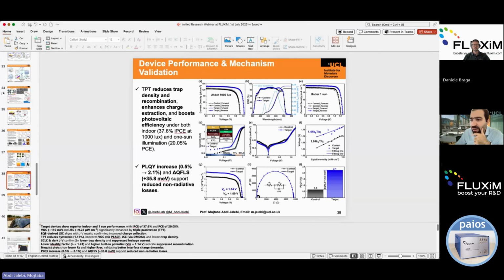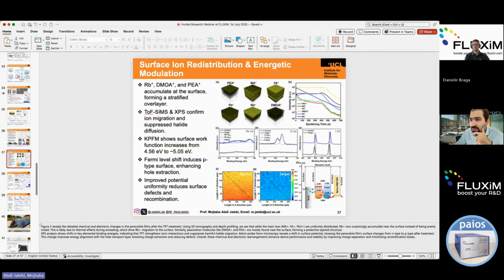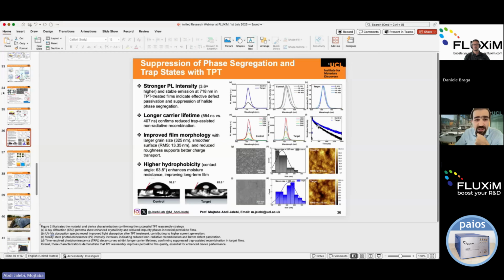It's more of a direct observation for the ion migration, I would say. If you have ion migration and phase segregation, that will definitely show up in your PL, because if you have two phases of large gap and low gap, the luminescence you get from your semiconductor will normally come from the lower gap, as observed extensively in the field.